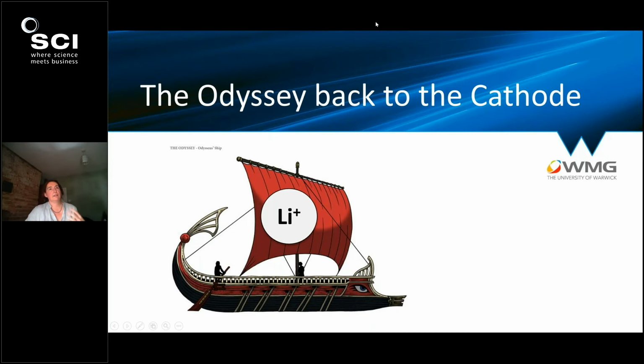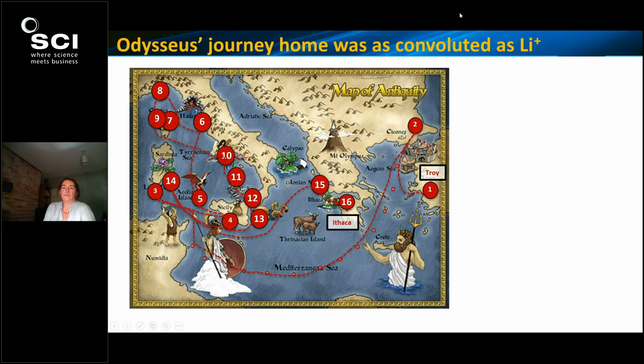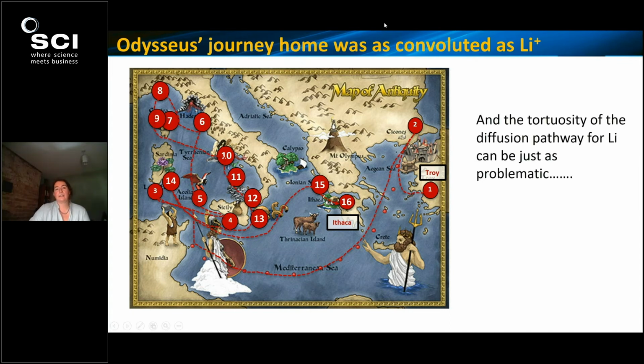So then, after the Greeks did that, the massive journey back towards Ithaca for Odysseus formed the second part of this epic poem. So let's see what that looks like for lithium ions. This is a map of the journey from Troy to Ithaca for Odysseus in the Odyssey. And as you can see, this journey is a little bit convoluted and not exactly as the crow flies, as we say. But to be fair, the tortuosity and diffusion pathways for lithium ions on the way from the anode back to the cathode are as problematic and tortuous.